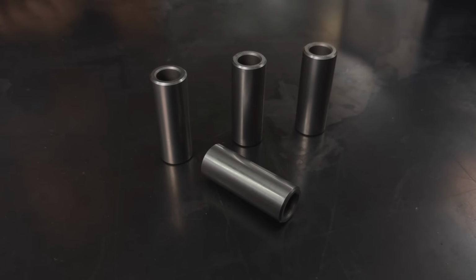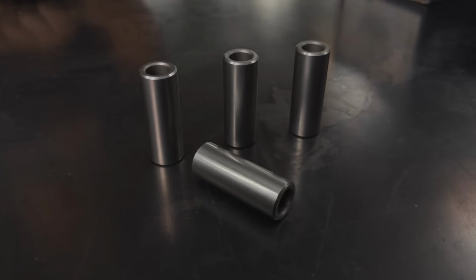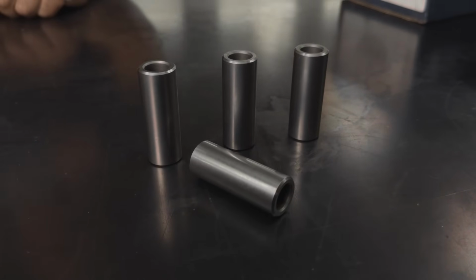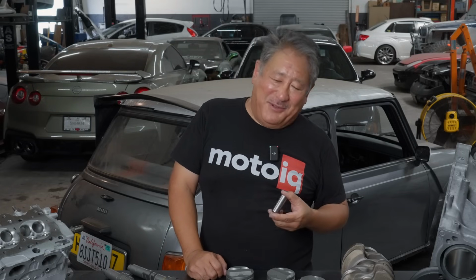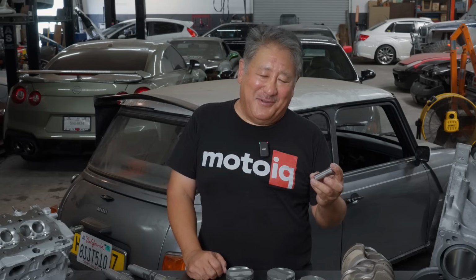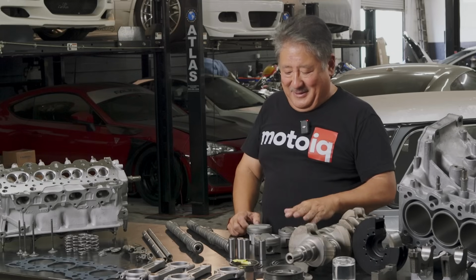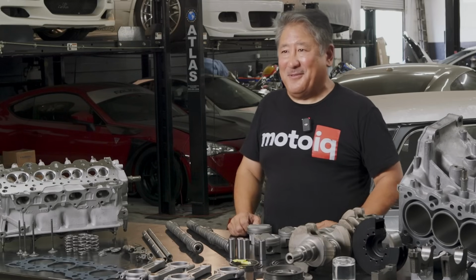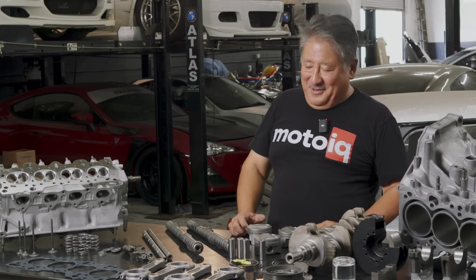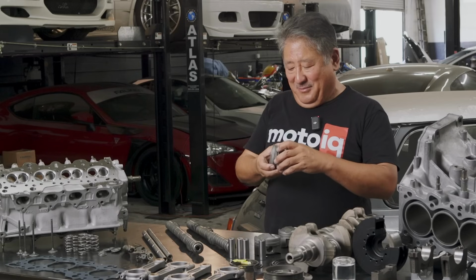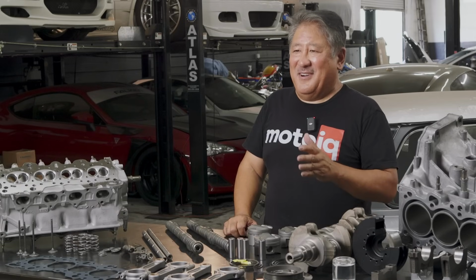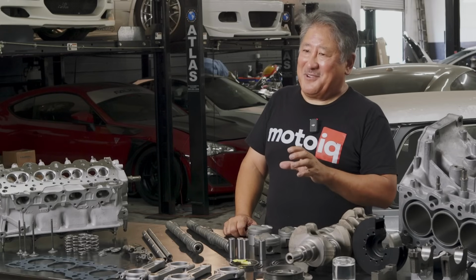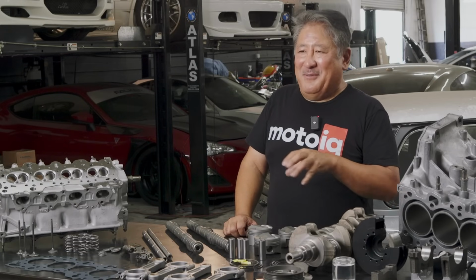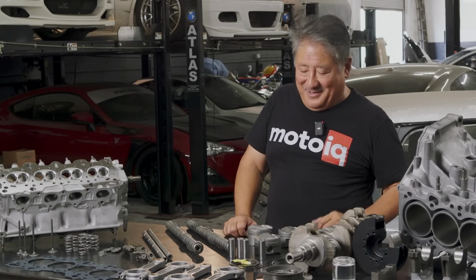For the piston pin, we're running JE's standard straight wall piston pin. I don't really believe in running tapered super thin pins because a lot of times with high load they'll flex and they'll screw the small end bushing out of the rod. So I'd rather sacrifice a little bit of weight and have a stiffer pin. The pin, the piston, the rings have all been WPC treated for long life and low friction. What I really like about the piston is when you WPC the grooves, you get a nice hard dimpled surface in there and you're less likely to get micro welding. Your rings are a lot freer, they move around nicer, and you get better ring seal and ring life.